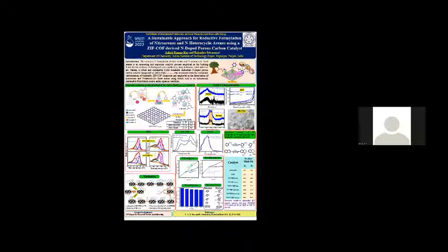That is, the COF is mainly the source for nitrogen and carbon. Further, in order to modify the carbon framework and nitrogen framework of the ZIF, first the bimetallic ZIF, that is zinc and cobalt, with varying amounts of metal concentration was prepared. Then the resultant COF-ZIF material was carbonized in an argon flow in order to get the bimetallic embedded and doped carbon.